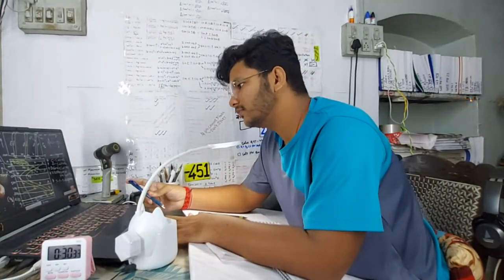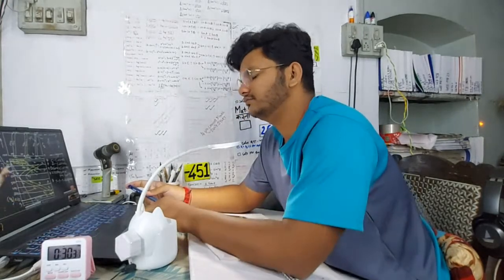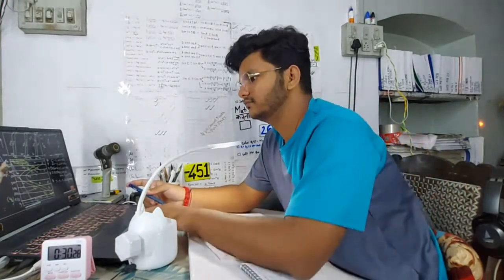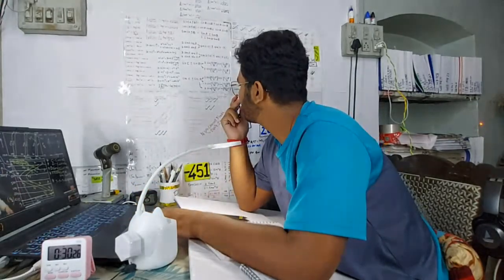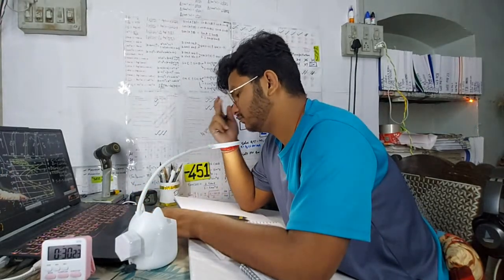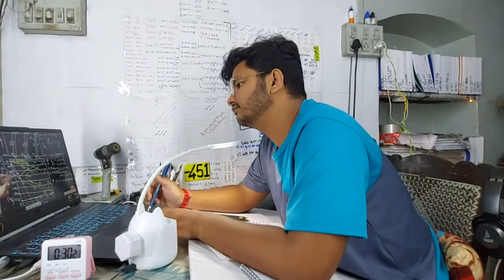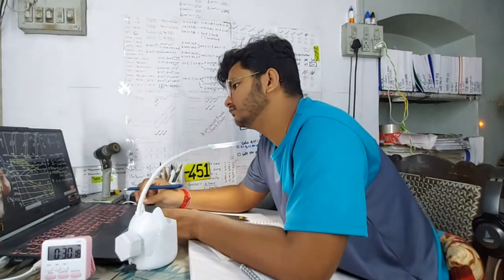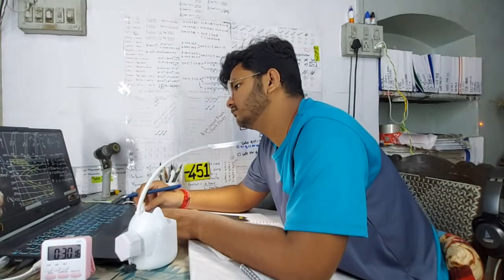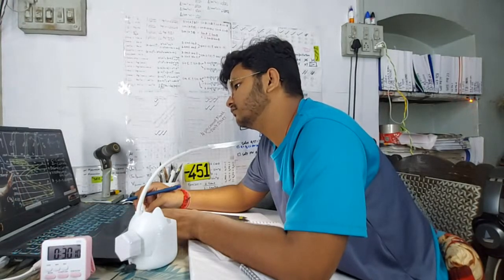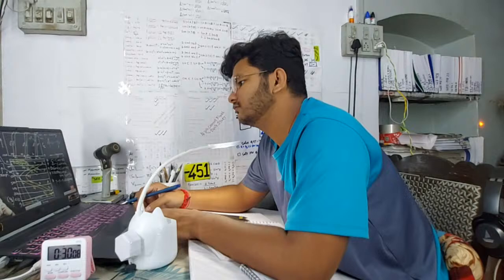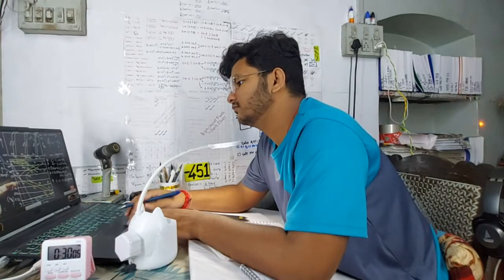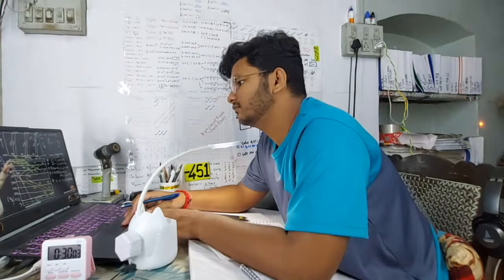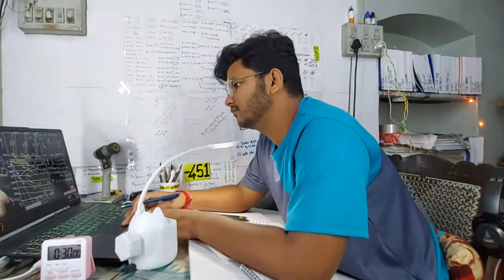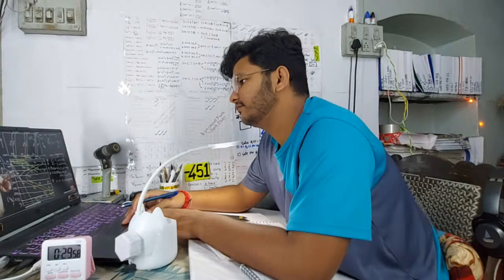So, what is the critical cooling rate defined as? Critical cooling rate is defined as the minimum cooling rate which is required for direct conversion of austenite into martensite. बोले तो martensite directly पाने के लिए austenite से कम से कम कितना cooling rate apply करना? If you apply a cooling rate more than the critical cooling rate, it is still fine. You will get martensite only, right? But the minimum cooling rate that is required for direct conversion of austenite into martensite is called the critical cooling rate. Point is clear to you?